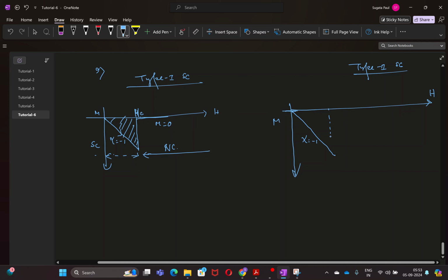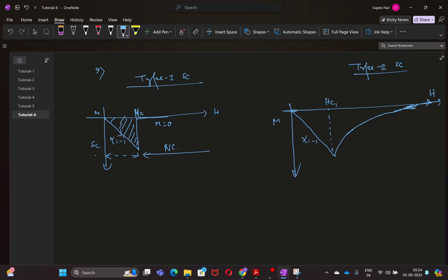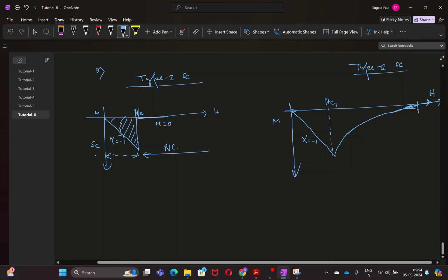Then after a point in the field which is marked as Hc1, critical field 1, the magnetization versus H is not like a simple negative slope straight line, but it starts to fall off, although not completely to 0, and it has a different kind of behavior. Gradually it approaches the 0 value, so that it tends to touch the x-axis at some point. We mark the point where it touches the x-axis as Hc2.